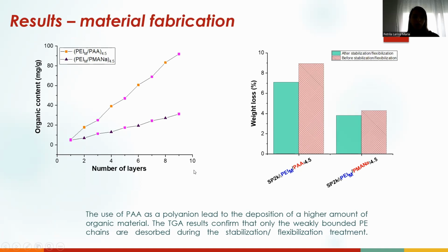The successful fabrication of the composite materials was assessed by using the polyelectrolyte titration method to calculate the amount of organic material that was deposited after each step. We can observe from the graphical representation on the left side of the slide that when using polyacrylic acid as a polyanion, the amount of organic material deposited on the support microparticles was much higher due to the high molar mass and the coiled conformation of the polyelectrolyte, which favors the deposition of thicker layers. On the other hand, when using polysodium methacrylate as a polyanion, the amount of organic material deposited was much lower, this polyelectrolyte having a lower molar mass and a stretched conformation.